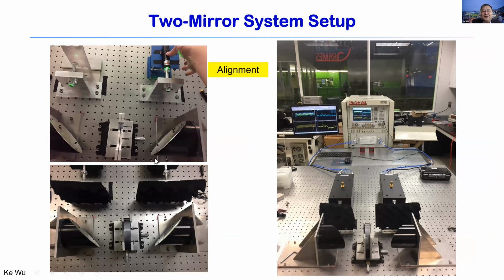At the same time, before everything, we also have to make sure that we have very accurate alignment and distance. So two things: one is alignment and the other is distance. Distance can be guaranteed through the optical table, but alignment also has to be done properly, because small misalignment for terahertz system measurements is very delicate. So we use a laser technique to do the alignment here.